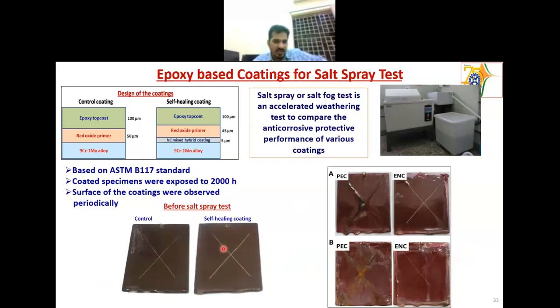Say the ASTM standard is there, and they make the coating cut in such a way that the steel surface should be exposed. These are the set of coatings we made, and these are after 1,000 hours. We found that in the control coating the blistering happened, it peeled off, and a lot of corrosion happened. In the nanocontainer based coating, we could see that only at the edges some corrosion had happened, and in this area nothing happened.